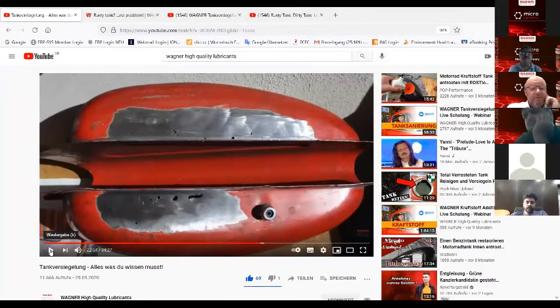So this is a normal situation. You can see, especially in the bottom of the tank, we have several holes. To weld those holes is possible, but the metal thickness here is not very big, and once you're welding, it could be possible that the hole becomes bigger. And once you put temperature inside, you can produce more cracks and sprinkles, which is the next issue you have to solve. Therefore, we try to reduce that, or try to weld a tank, and to refurbish that with, for example, a glass-fibre mat. I will show you.